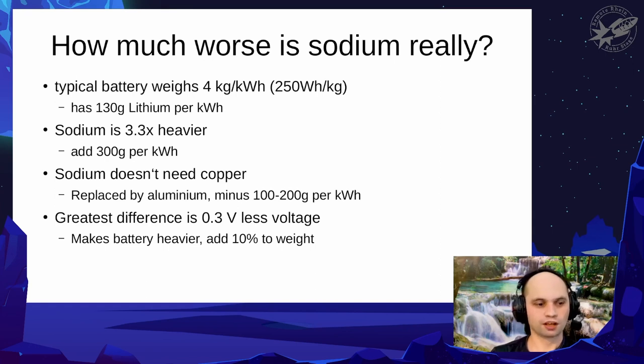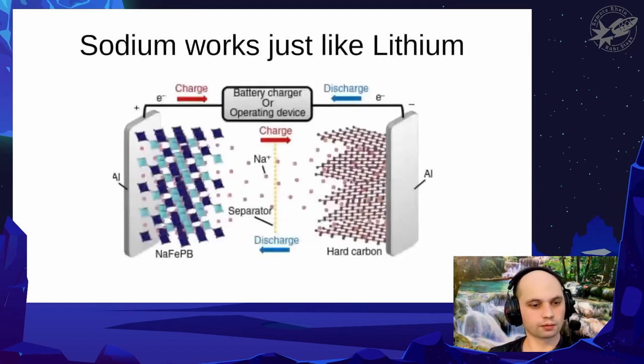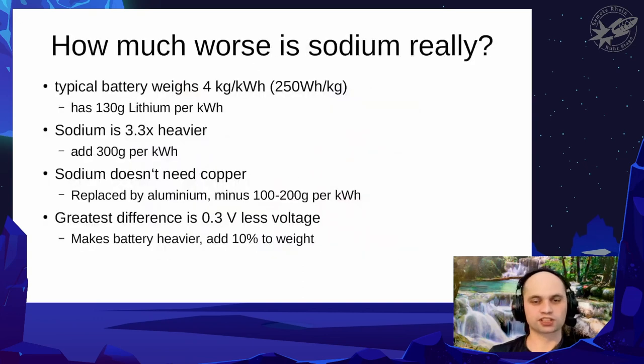It's not that much. And also, when you use sodium, you don't need copper. As you have seen on the other slide, both sides are aluminium. Normally, on the right side, with the hard carbon on the anode, you would need copper because lithium just combines with aluminium and starts to destroy it. So you cannot use aluminium, so you use copper. And copper is much heavier, and so you're saving like 100 or 200 grams of material by replacing it with aluminium. And so the difference is just almost negligible.